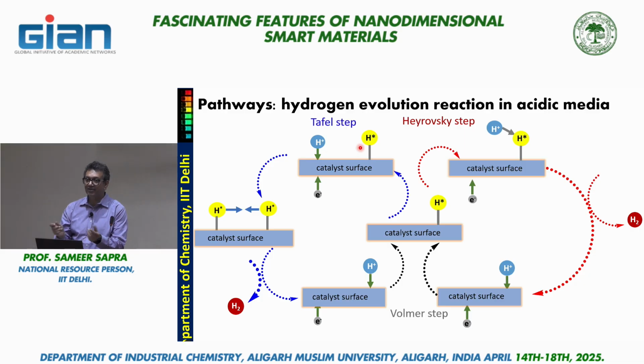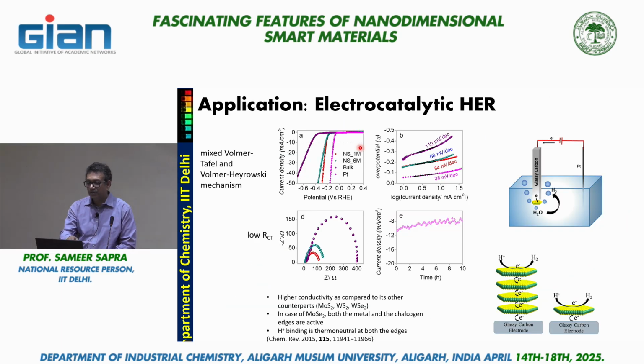It requires more potential. This is a much easier step. And now if I have created so many defect sites on the surface, which one is going to be more favored? Is the Tafel mechanism. If the Tafel mechanism is favored, then you will have much more hydrogen evolution reaction. And that's what is happening, that the inverse of the slope of this is a small number. The smaller the number, the more hydrogen is coming out at larger potentials. So somehow you promote the Tafel mechanism.